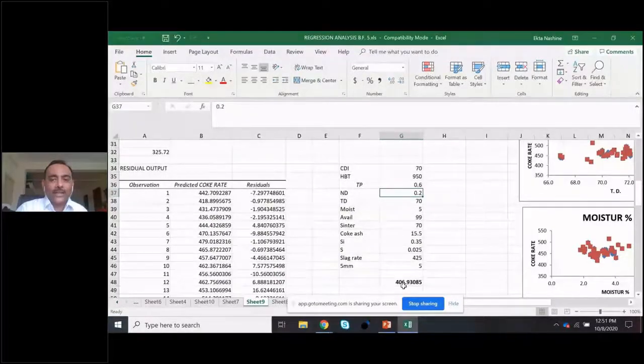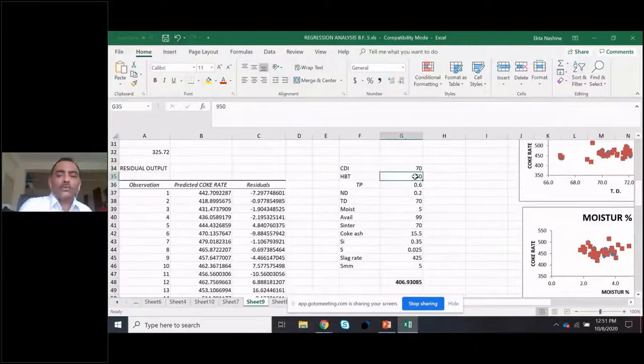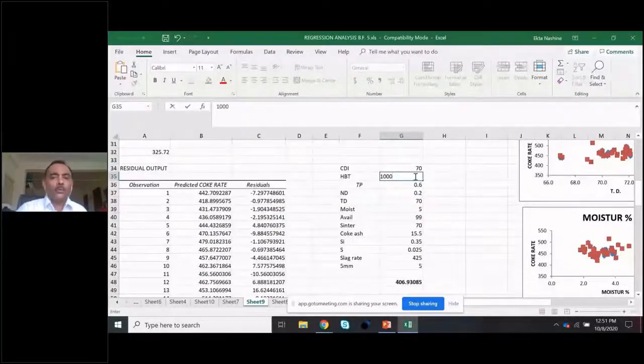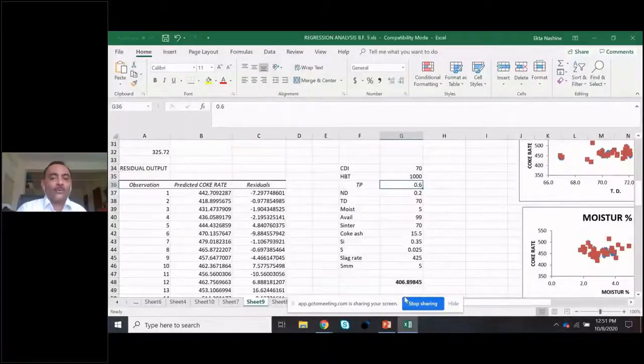Same in the case of hot blast. The air which we are sending inside the furnace is at 950 degrees centigrade. Somehow, with the help of a very good gas air ratio, or stove modernization, or stove maintenance, whatever way, I am able to make the hot blast temperature 1000 degrees. See, the coke rate reduces, but not too much: 408 comes to 406, although I have improved the hot blast temperature by 50 degrees. Previously, we thought it was a very, very important factor. Then we realized it is an important factor, but not as compared to top pressure, not as compared to silicon. So this is the beautiful part. By the regression analysis, we know what the positive factors and what the negative factors are.